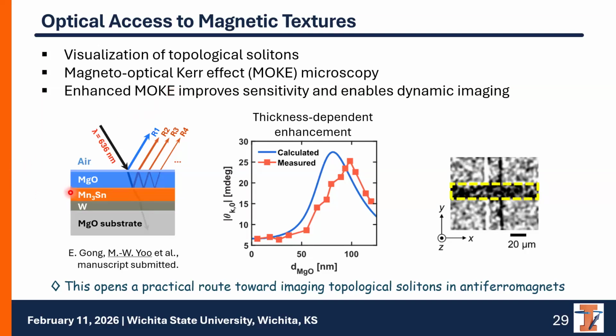So in this work, my undergraduate mentee and I demonstrated that optical interference engineering using a dielectric layer, in this case MgO, can significantly increase the Kerr signal, like this. So careful control of the optical stacks can achieve a very high enhancement factor, more than 4, of the Kerr signal. And these results can open a practical route for topological soliton visualization in antiferromagnets.